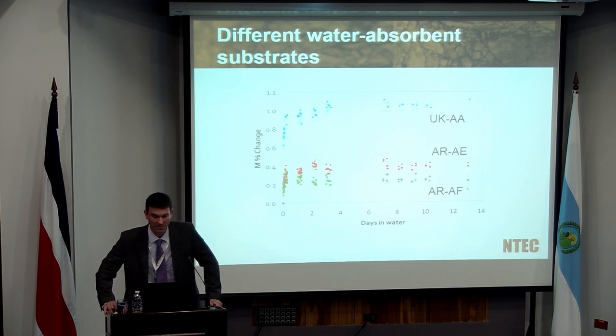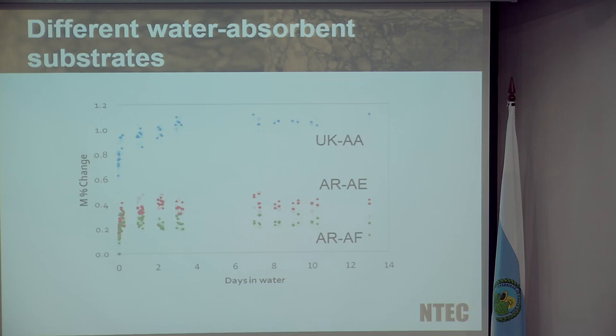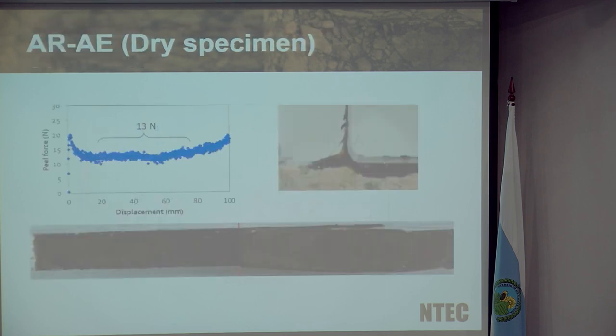I've got two different types of aggregate there in terms of basic materials. One is a limestone and two of them are granites. And the two granites, which are labeled AE and AF, have different diffusion rates. So although they were nominally the same in terms of their mineralogy, their chemical composition and their nature, they were very different in terms of their moisture diffusion. And can we see the effect of that in terms of results?